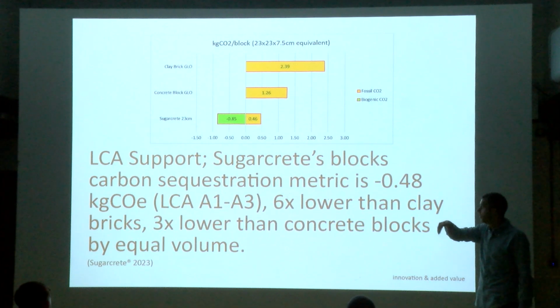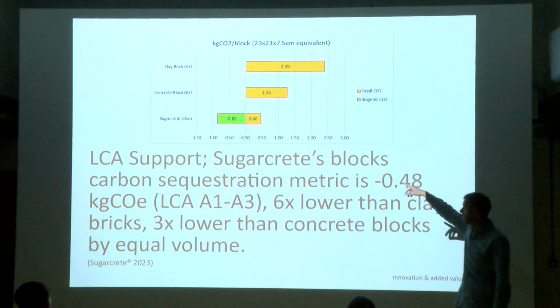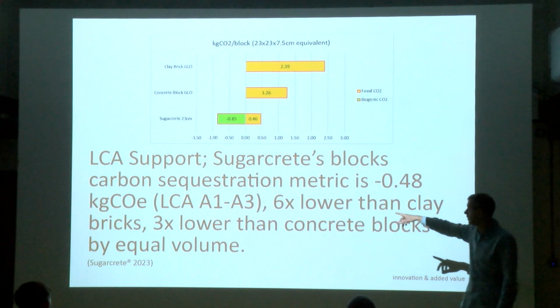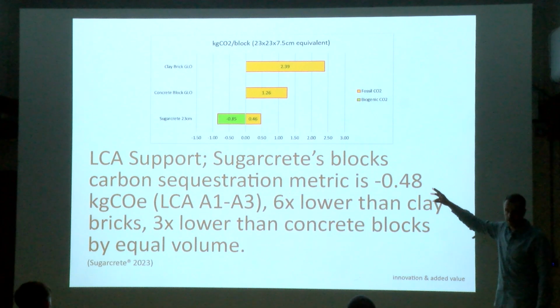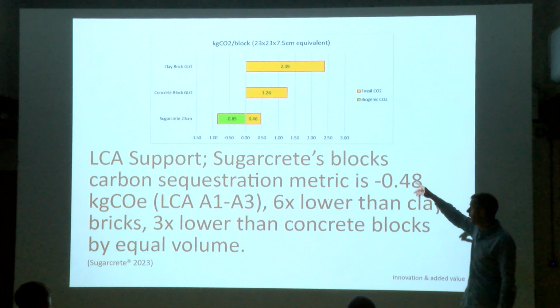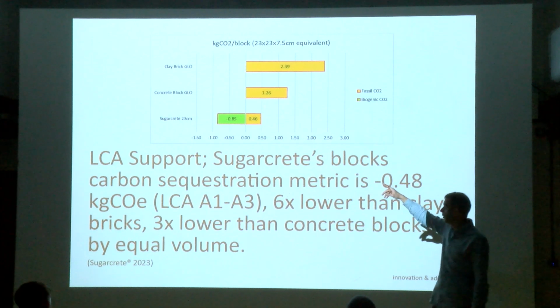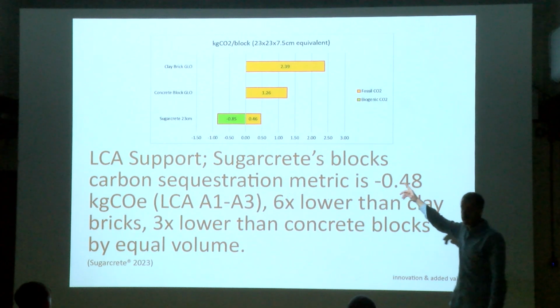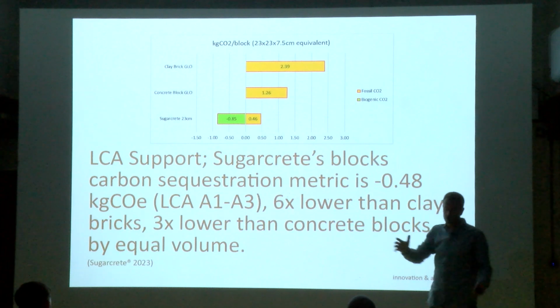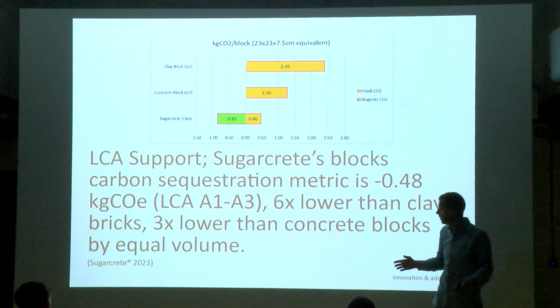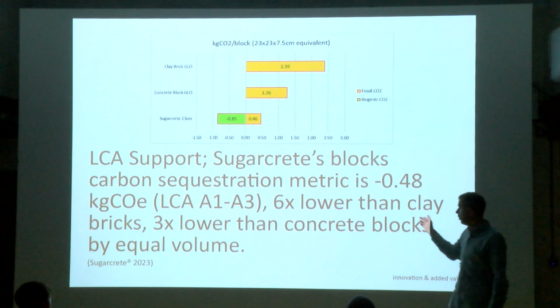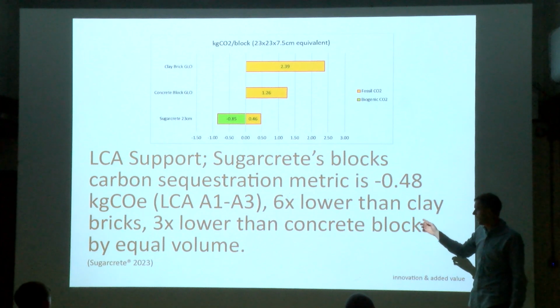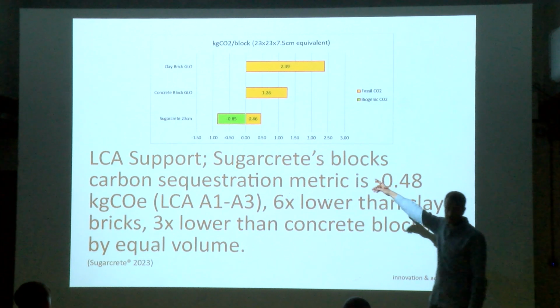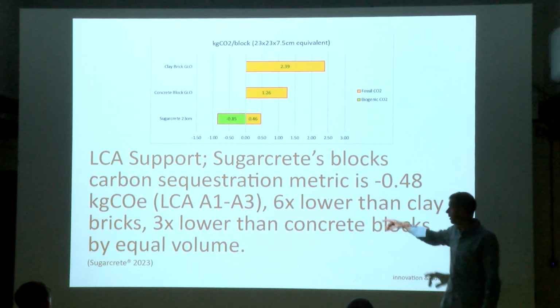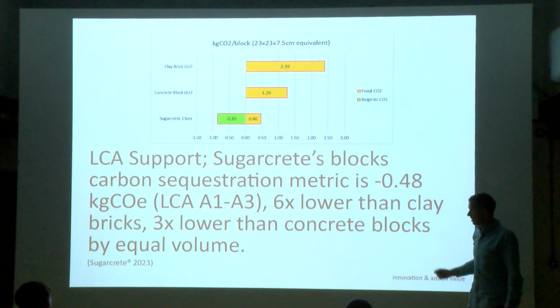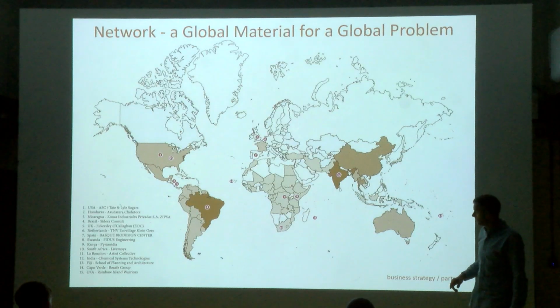The block that you are passing around, this is the life cycle assessment that we did, A1 to A3, assuming that they are fabricated locally in India, and compared with a concrete block fabricated locally and with a clay brick fabricated locally, compared by volume, so using the same volume of material for the three of them. It is 6 times lower than clay bricks and 3 times lower than concrete blocks, and it is carbon negative. So it's the only one of the three that is carbon negative. And that's the amount that is sequestered per brick.